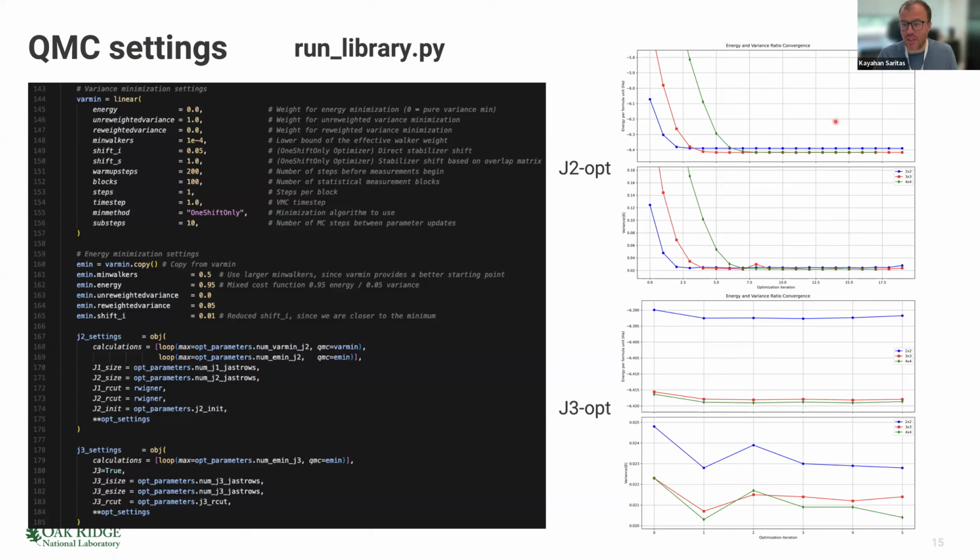One thing that you can see is that I'm plotting the energy per formula unit. For VMC, the 3 by 3 and 4 by 4 supercell sizes have very similar energies, but 2 by 2 has a different energy than those. So it may indicate that wave function quality is improving as you go to larger supercell sizes. And that is also prevalent, although it is a little bit more difficult to see.